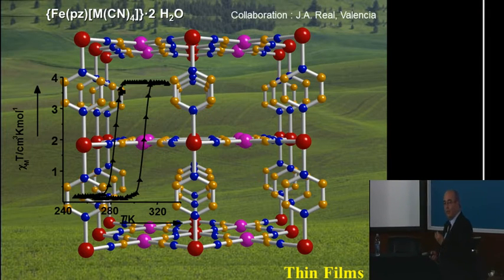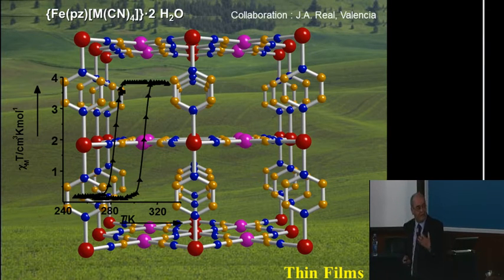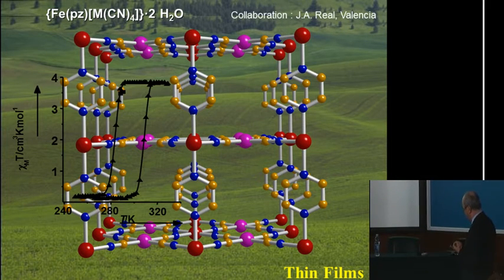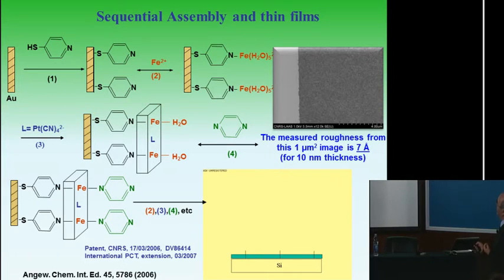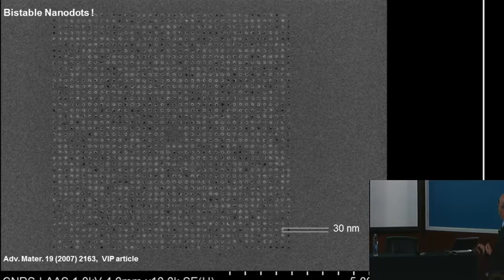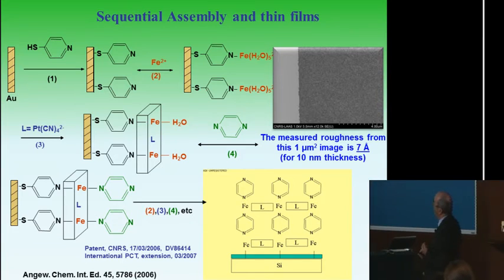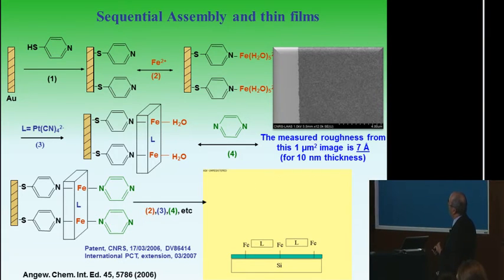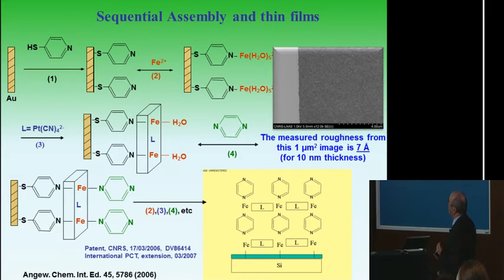And then what we said, why don't we take mercaptopyridine, fix it on the surface, and try to make layer by layer sequential synthesis slowly to try to fix these materials on the surface and try to see if we can maintain our hysteresis loop, okay? So then it's exactly what we did. So then we took mercaptopyridine, we fix it on the surface, we bring the iron salt, okay, and then the iron platinate, and we come back with pyrazine. And as a function of how you turn sequentially, layer by layer, you are growing your system, okay?